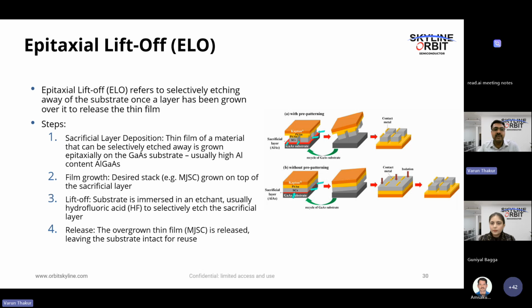So we use a solution which only etches away that specific layer, and we grow that on a gallium arsenide substrate. So usually it is a high aluminum content aluminum gallium arsenide, and then on top of this, because it is already lattice matched, we can grow a solar cell on top of it. It grows very nicely and it will give you a very good efficiency. And then, to use this substrate again, we dissolve the aluminum gallium arsenide sacrificial layer. How? By dissolving it in hydrofluoric acid. This does not affect your overlayer, which is the solar cell, and then you get the substrate back. So you can use the substrate again.